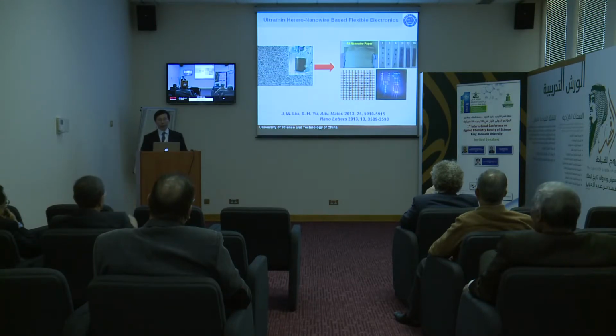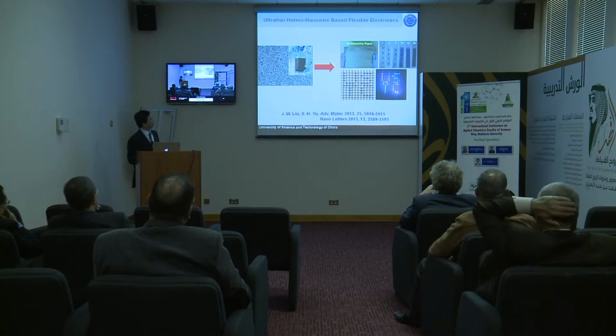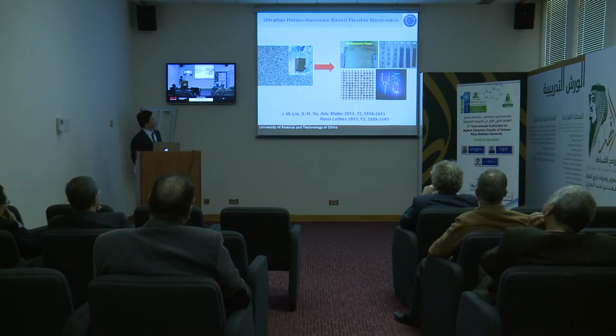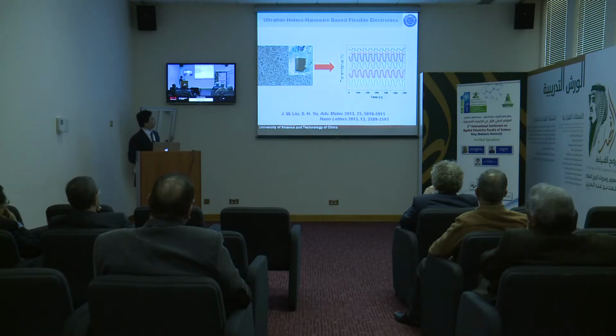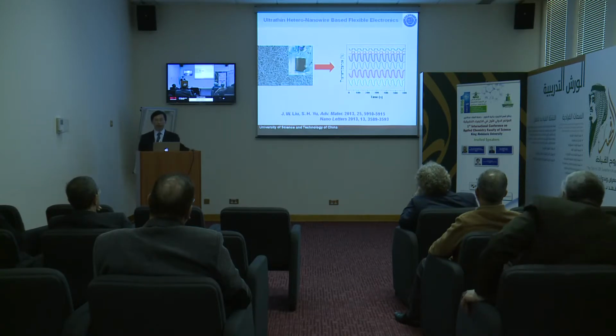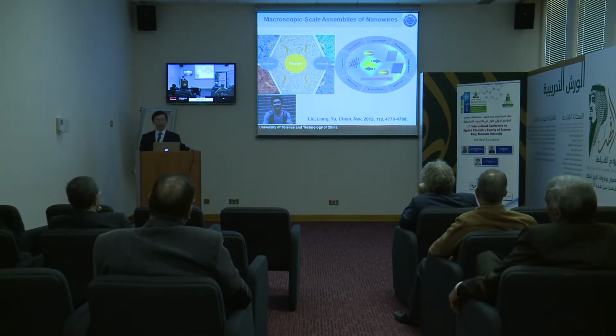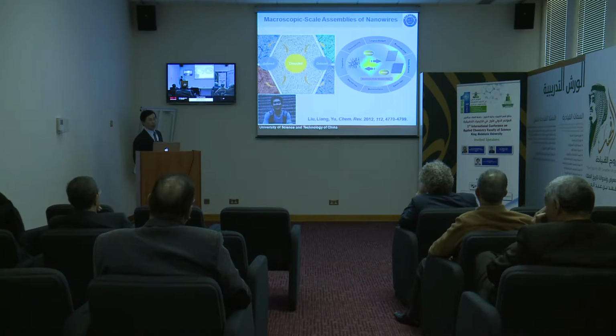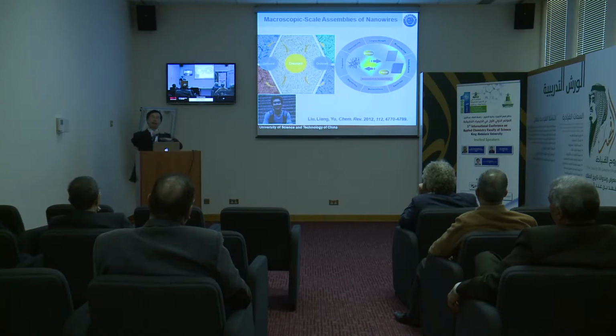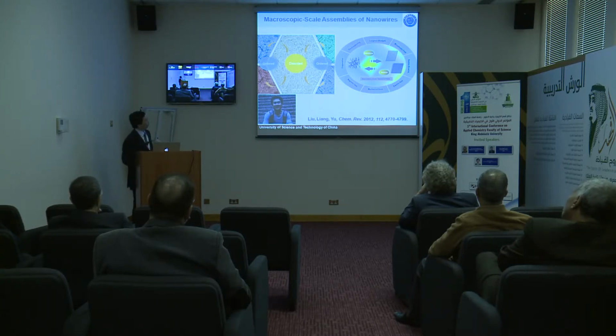And lastly, I show you we're using these nanowires. You can even coat A4 papers. You can make your A4 papers become conductive. You can even use this substrate for very reliable device applications. You will see some data is really very promising. So the concept is very easy: make this disordered nanowire become ordered. Because if you get ordered nanowires, then you can get different thin films with different hierarchical structures for further device fabrication in the future.